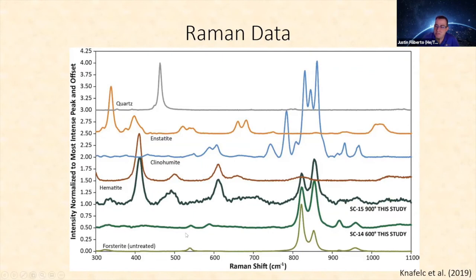You can see the 600-degree experiment still has this nice olivine doublet, though the doublet has shifted with the right peak being higher than the left peak. You can see other peaks starting to form. These are consistent with the formation of iron oxides. For the 900-degree experiment, first of all, we've got a lot more noise. However, you can still see this nice doublet here. So the Raman is still seeing olivine, but this is hematite, and you can see we are getting the peak here, and this giant peak here. And so it's consistent with the formation of hematite.